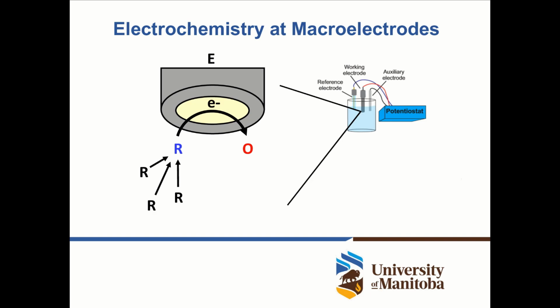Here you see on the left-hand side a scheme of such a working electrode. The yellow part is the metal, and we can apply a voltage to this metal and drive an oxidation reaction. Here we show the diffusion of a redox active species in solution towards this electrode, where it gets oxidized. These redox reactions involve electron transfer reactions. So we are basically counting electrons and can thereby quantify the reactions that happen at the electrode tip.